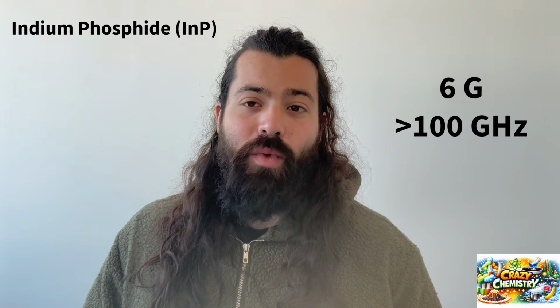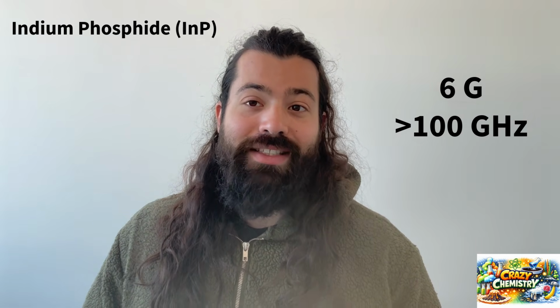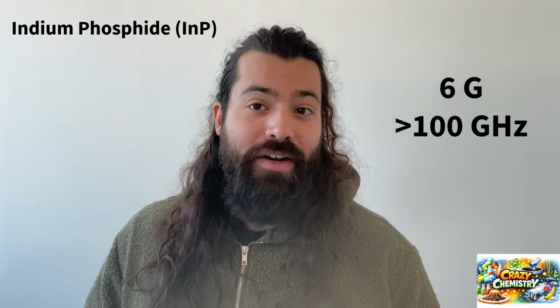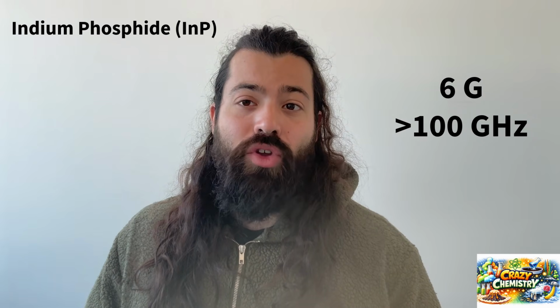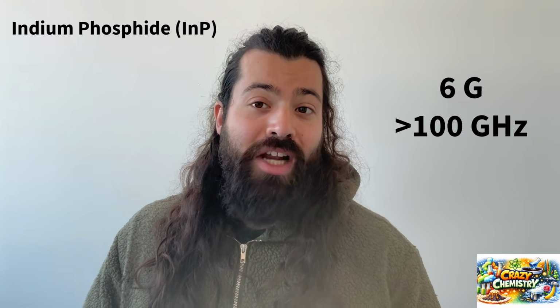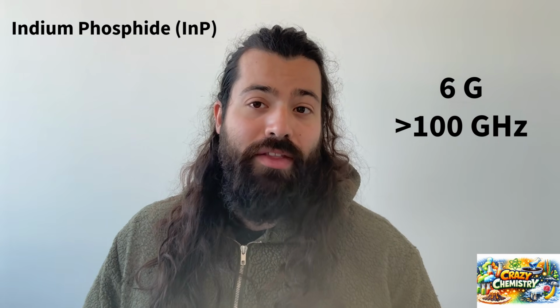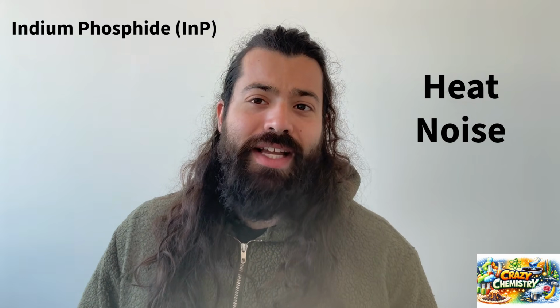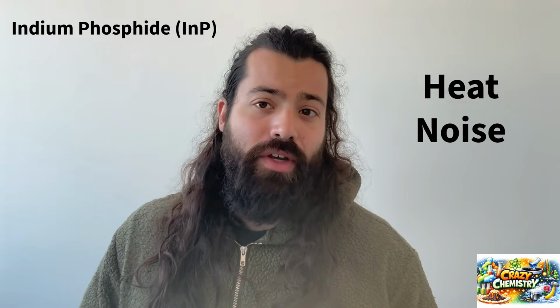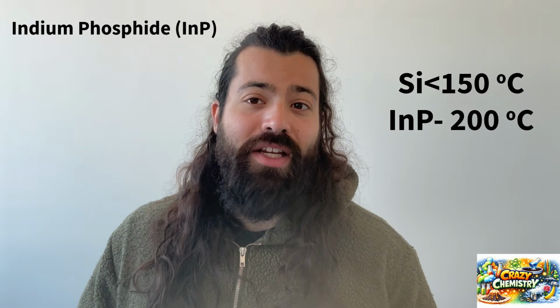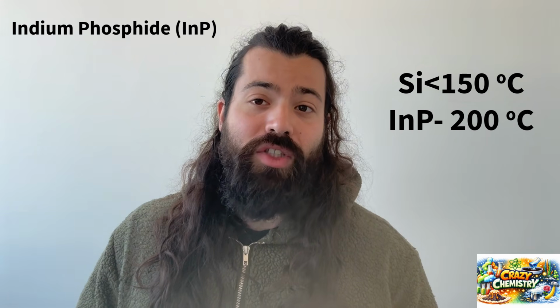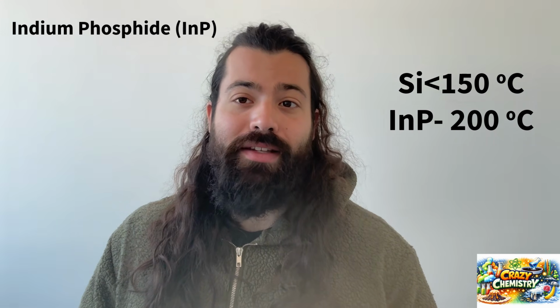6G targets frequencies above 100 GHz. Some bands push towards terahertz. At those speeds, silicon stops being a semiconductor and starts being a problem. Indium phosphide, though, keeps going. Two more things engineers care about are heat and noise. Since indium phosphide has a higher bandgap, it can keep being a semiconductor at higher temperatures and can withstand more heat. Silicon devices start failing at about 150 degrees Celsius, while indium phosphide keeps working past 200 degrees Celsius.